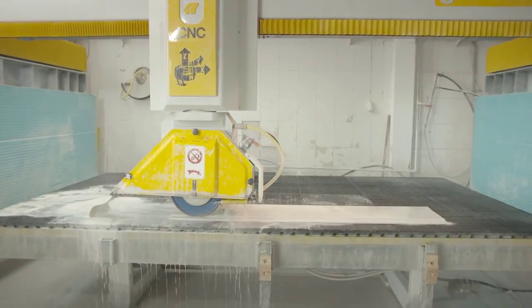The thickness to which you reduce the Caesarstone depends on the radius you want to achieve. In general, the smaller the radius, the thinner the Caesarstone will need to be. The thickness will generally be between 2 and 5 millimeters.